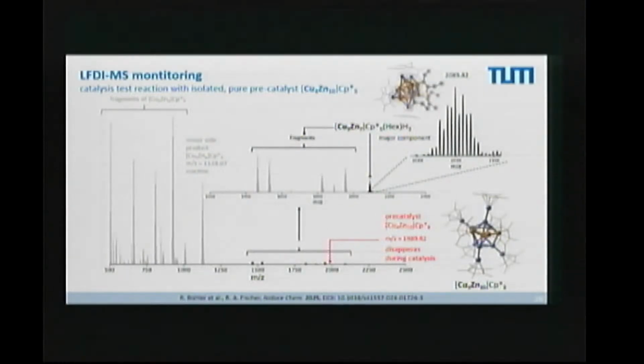This is the molecular ion. This is the isotope pattern of this particular thing. And these gray ones are all the fragments we can assign to the fragmentation of this peak here. And all these grays here are also fragments which come either of the fragmentation of this or a nasty impurity. This is an impurity, we cannot get rid of it, but this impurity is not sensitive to the alkyne and the hydrogen. It stays. So we have an almost pure situation.